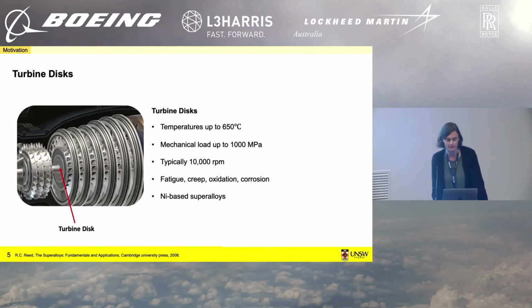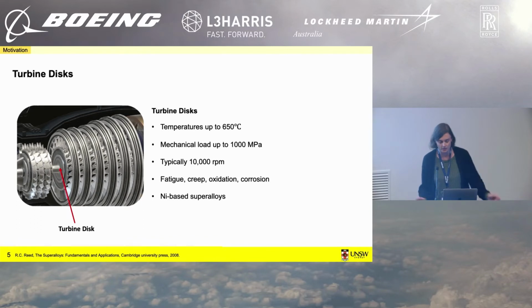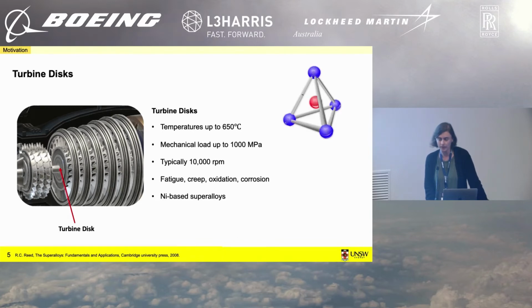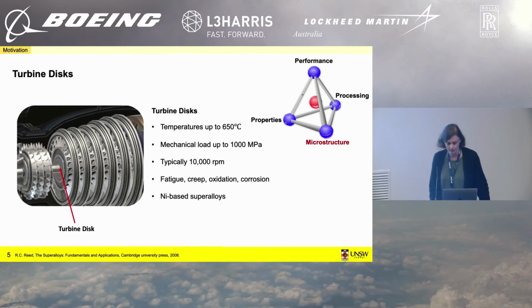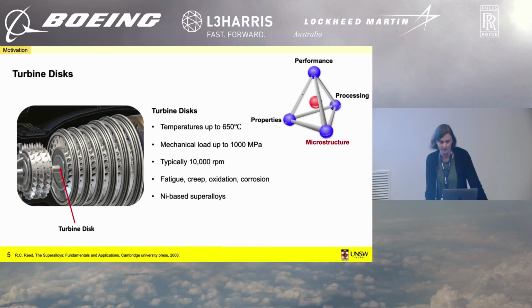And in order to increase the efficiency of the aircraft engines, we want to have high temperatures, so ideally above 650 degrees C. There's high mechanical loads, fast rotation, and then there's very harsh environments, so fatigue, creep, corrosion, oxidation, and all that. And therefore, we need so-called nickel-based superalloys to build these parts. So in order to make better turbine discs, we need to understand the interrelationships in materials engineering. So what we want is obviously better performance and better properties. We can tweak the processing to achieve that, but the really kind of missing link between all of those is microstructure, and that's what my team and I are pretty good at.